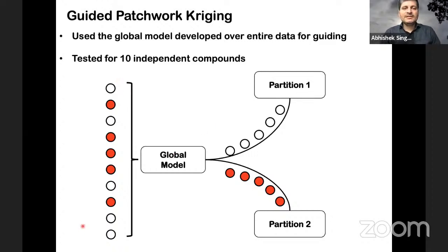So we tested this model on 10 unseen compounds like this. Our global model was able to send them to the right partition very nicely. So here's an example. And then these two, the models for partition 1 and partition 2, did a very good job of predicting their thermal conductivity.